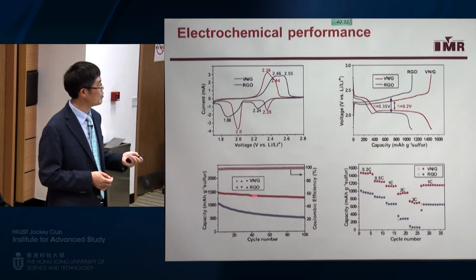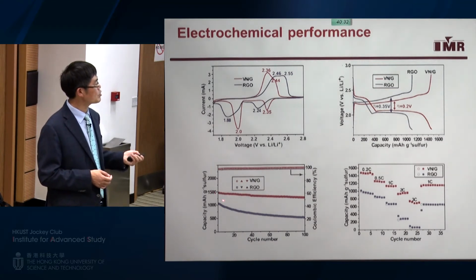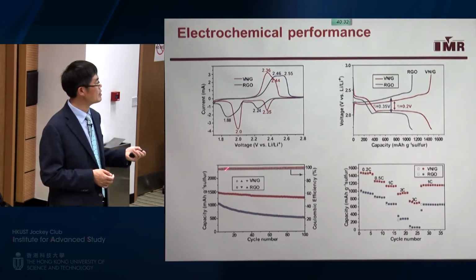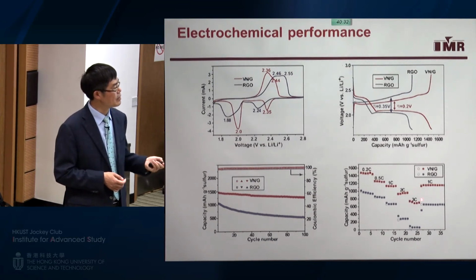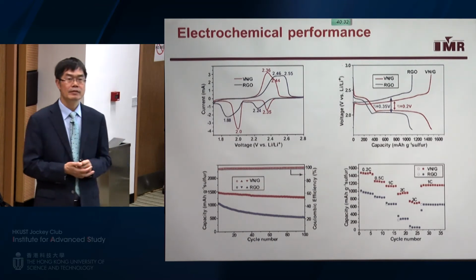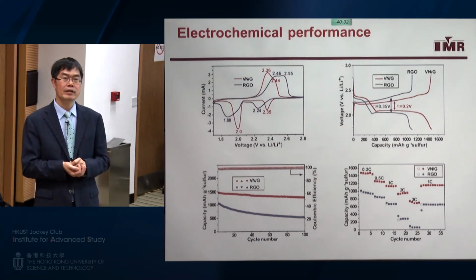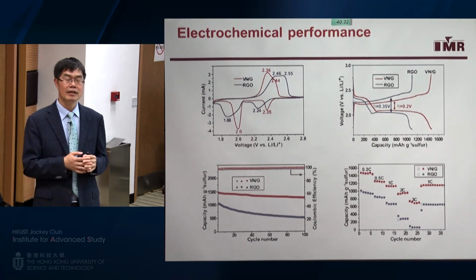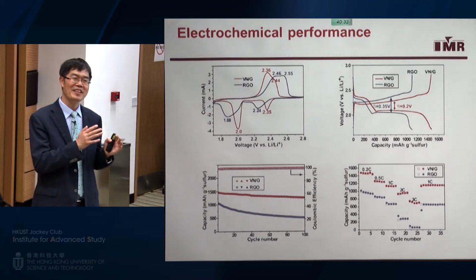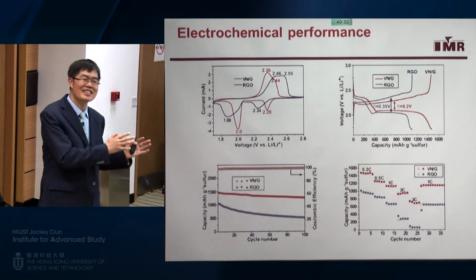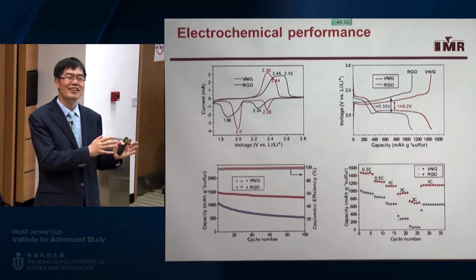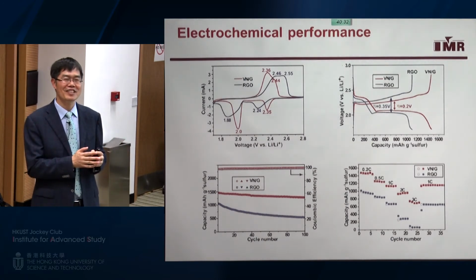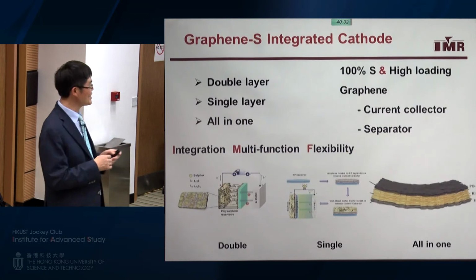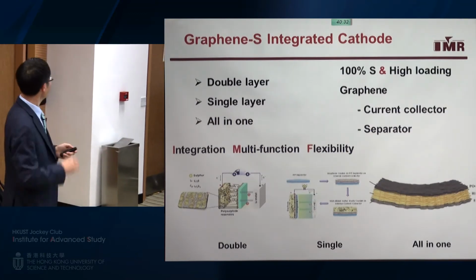Here I show you the performance. You can see the performance is very high. It's more than 1,200 capacity, and also the rate capacity is good. So that means this kind of approach is useful for lithium sulfur battery. But again, if we want to use this kind of material in a practical lithium sulfur battery, it's not so easy. So we always think of some easy way.